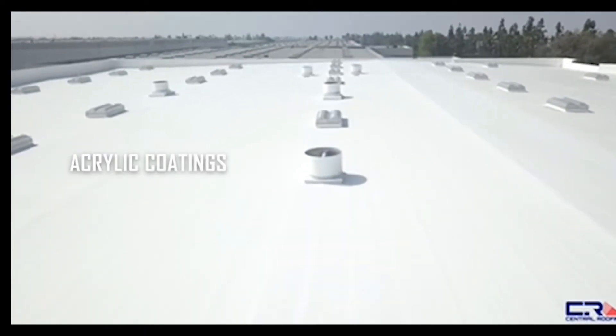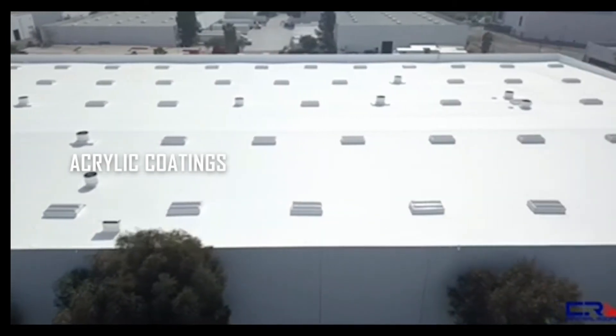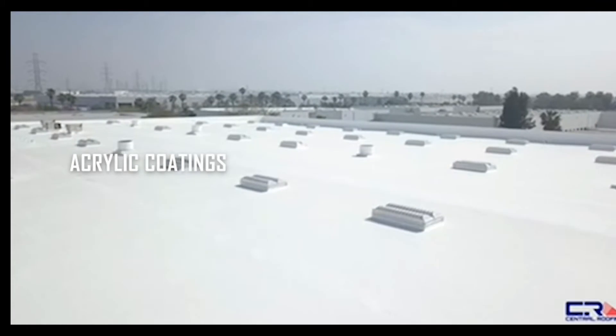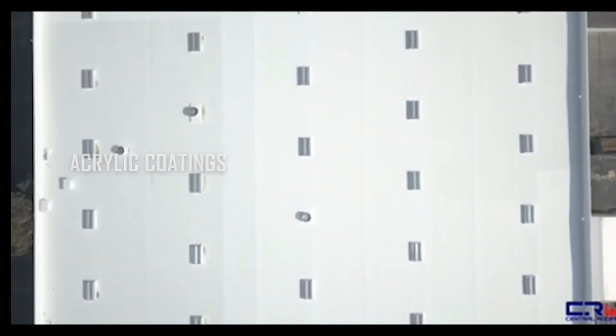Additionally, they are easy to clean up and are less harsh on application equipment. However, they do have some drawbacks. Acrylic systems are prone to lose thickness as they age and need to be installed when outside temperatures are 50 degrees or higher to achieve maximum adhesion.